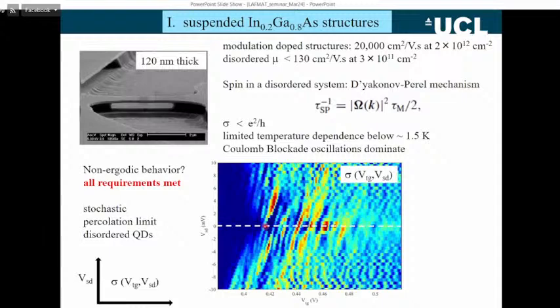And we have something called a charging diagram. So what happens is when we apply a DC voltage in millivolts, we change the chemical potential in the source and the drain contacts at each end of the suspended wire. Okay, so we get these so-called Coulomb diamonds. It's a demonstration that this system is behaving as a series of anisotropic quantum dots. Now, it might be that spin is important in this system, but what's more important is that the conductance is just limited by this Coulomb blockade effect.